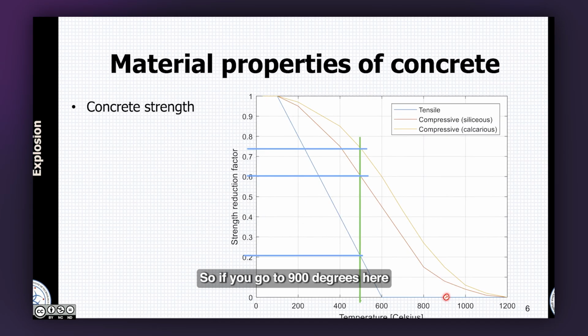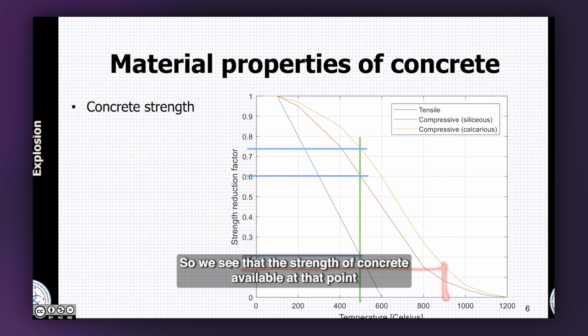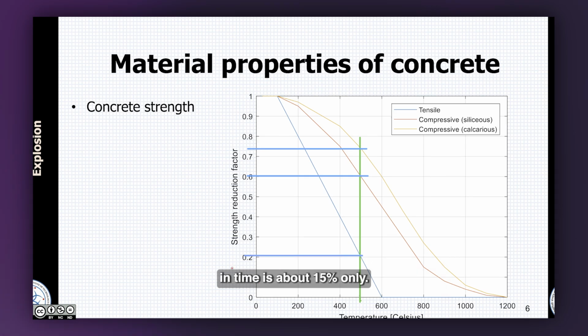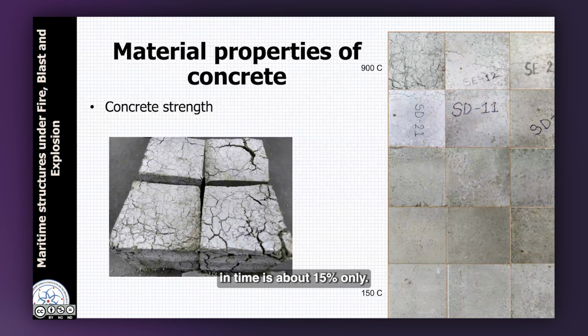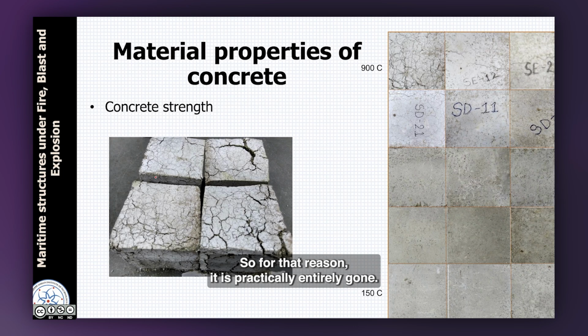So if you go to 900 degrees here, okay, we see that the strength of concrete available at that point in time is about 15% only. Okay. So for that reason, it is practically entirely gone.